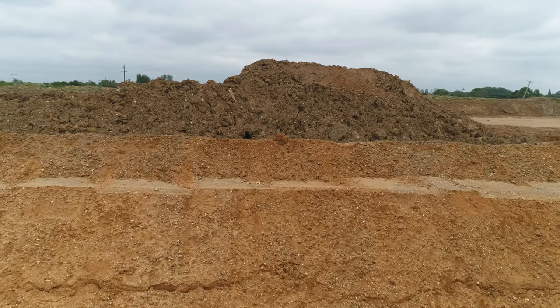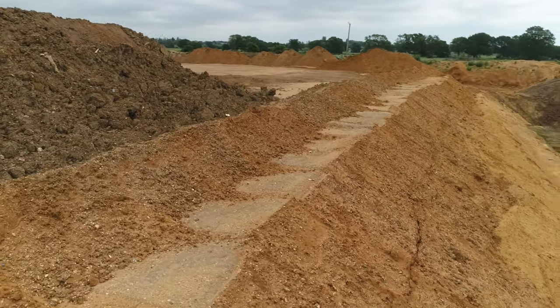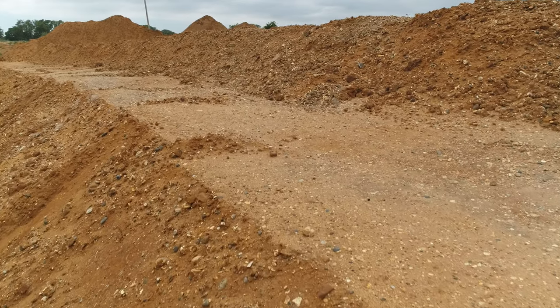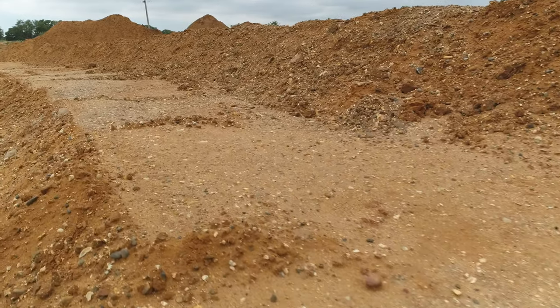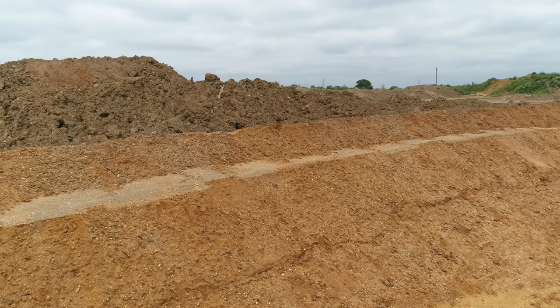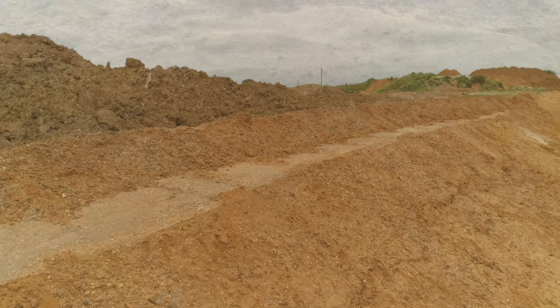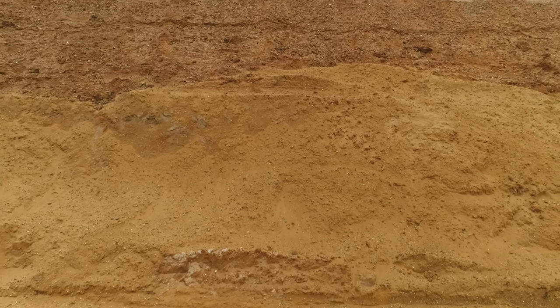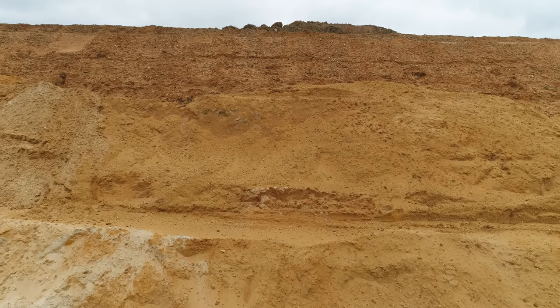So that top layer we're looking at now — Class 1A granular fill is its most common name. It meets various different gradings for different applications. Would you use this for concrete? For concrete, your aggregate has to meet certain requirements and this wouldn't meet it. As it is in its crude form, it's got quite a high silt content, which is no good for concrete whatsoever. And as you go through the seam, the mineral varies very much from very coarse and stony to pure sand to silver sand. You get the odd little strip of clay — it's just the natural strata that makes up the ground.